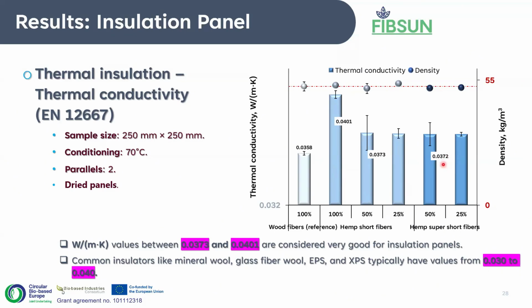So this is the thing. And what it tells us is that when we look at all the properties together, it's possible to incorporate these fines up to a 50% incorporation rate in the panel. So it brings another question: perhaps there is a need to also examine the 80% incorporation rate. If 100% is not so good, maybe 80% could also be something to look at.